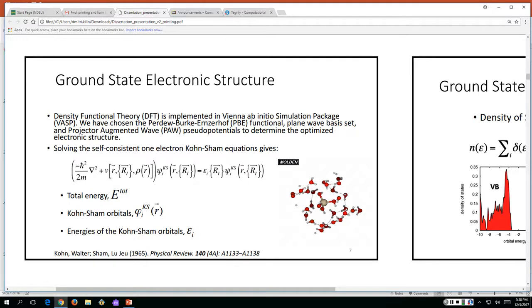I guess what is exactly your question now? So if you look at around 1 eV, it kind of looks like both spin orbit coupling and spin polarized transitions occur there. Right. So within this one additional electron state, if we look at the density of states for the spin polarized, we see that the alpha component looks pretty normal, but the beta component has an unoccupied state, like here. You can see that there's an unoccupied state here at about 1.5 eV. So that low energy absorption band for the beta is occurring from somewhere in the valence band to here.